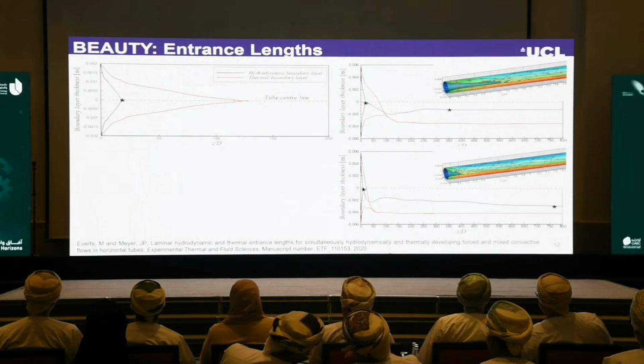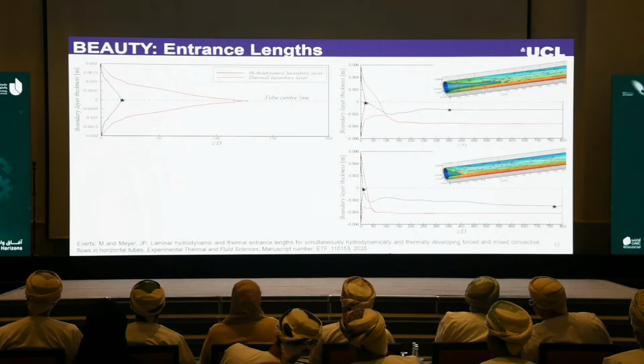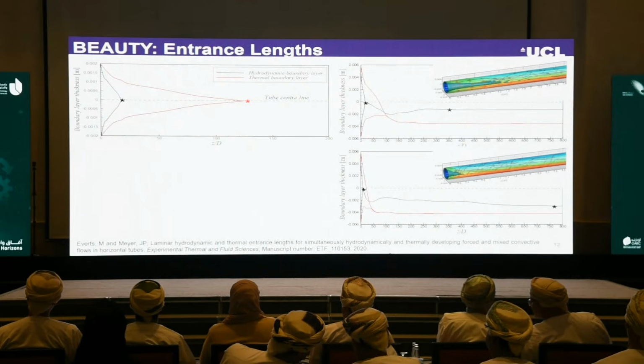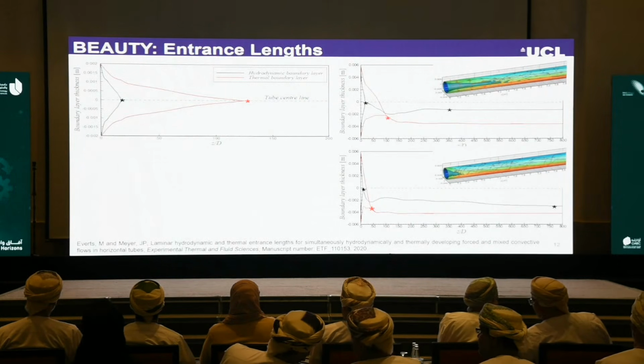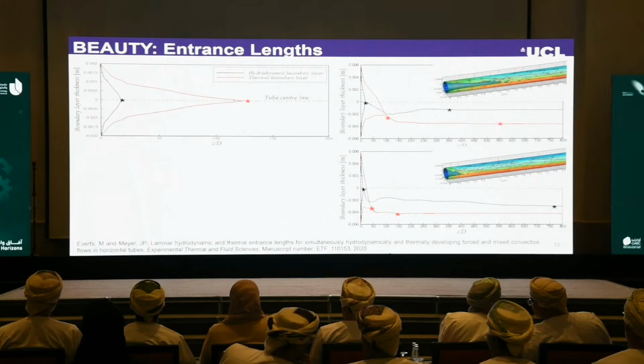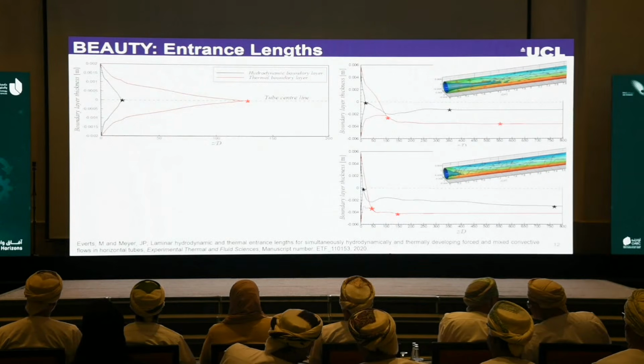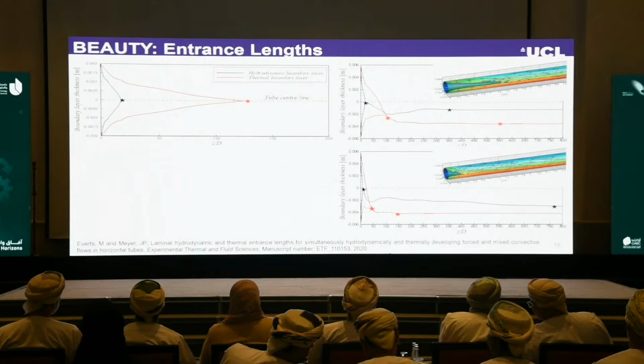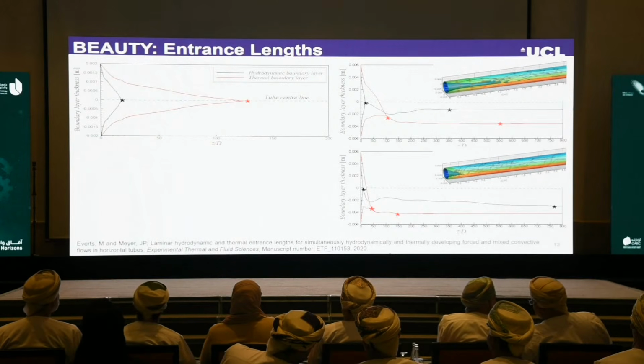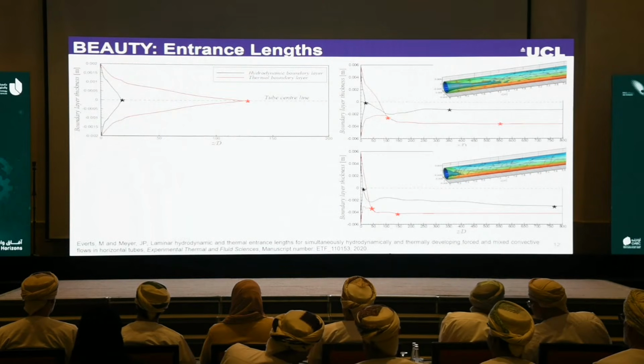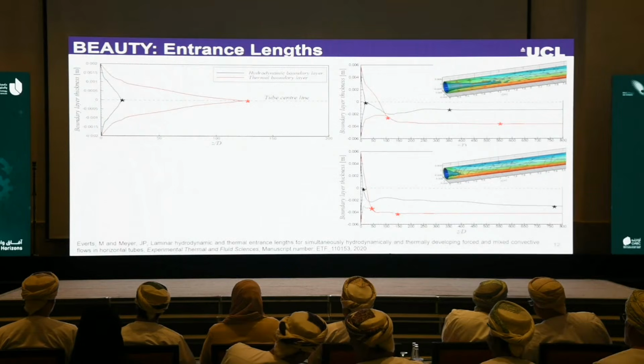On the other side, if we look at the thermal behavior, so now we're shifting to the red data, we see that, yes, for forced convection, it merged in the center of the tube, but for mixed convection, it actually shifted below the center line of the tube, and then this point shifted further downwards before the flow became fully developed. But now we're seeing the opposite trend as for the hydrodynamic boundary layers, whereas if we increase mixed convective flow by an order of magnitude from the top to the bottom graph, this point at which the flow became fully developed actually occurred earlier along the tube length.